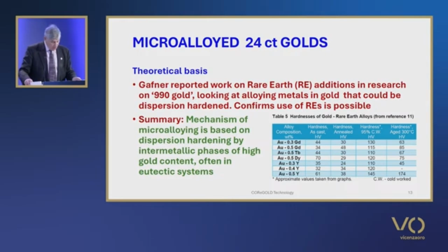However, in that work, a 1% alloying addition was being evaluated. If we consider only a 0.5 weight percent addition of rare earth, then from the solubility data at 400 degrees Celsius, we cannot expect much hardening phase to precipitate on annealing solutionized material at 400. Fortunately for us, Degussa carried out some tests on gold rare earth alloys at alloying levels of 1 weight percent and lower. Cast alloys were annealed at 800 for 1 hour. They were also cold rolled up to 95% deformation and subjected to age hardening treatments at a range of temperatures.